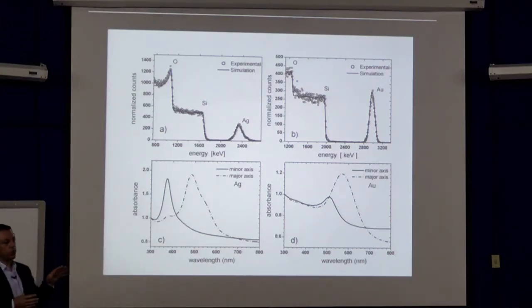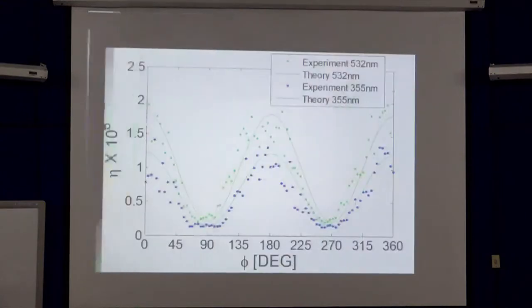So you can use this instrument to measure, if we have, for instance, here oxygen, silicon, silver, oxygen, silicon, and gold. These are the two samples that we are considering for the evaluation. And we have asymmetric shapes, and with the asymmetric shapes you can see that you can change the slope of the peak of the absorbance related to the surface plasmon resonance, and eventually use them to change the speed of the light in a system.